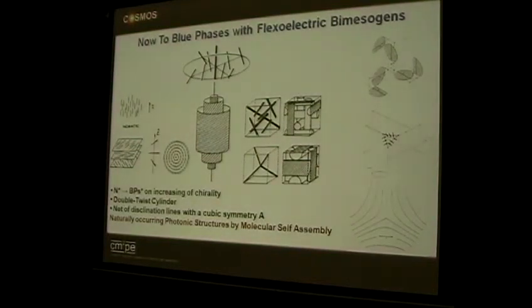One of them is that they are non-correlated, non-aligned cubes, scattering in all directions, but very small. But there are a whole range of theories if you read Peter Brooker's book on this. What's interesting for the blue phases is you form these double twist cylinders where, if you look down on the cylinder here, you've got molecules that are twisting around towards the center. Again, I tried to depict that there and we had that last week.